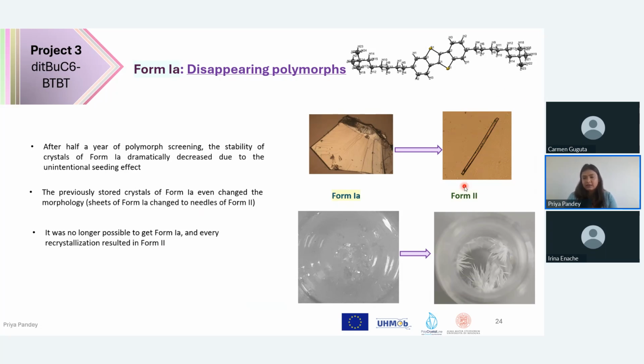So this is like needles. And I found that due to the unintentional seeding effect of this material, form 1A became dramatically unstable. Even the solvents and crystallization experiments that were yielding form 1A no longer yield form 1A, they just give us form 2. And this marks the disappearing polymorphs.